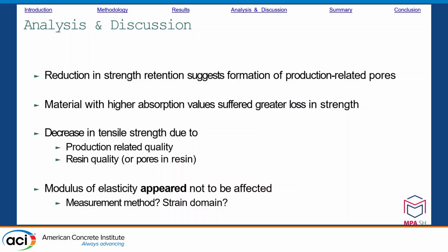In contrast to the resin matrix, here the test for horizontal shear strength, which focused primarily on the resin properties, shows significant losses due to frost exposure. The decrease in tensile strength is therefore caused more by the poor resin quality than by the fibers. Furthermore, the production quality also plays a decisive role here. Better results in the properties of the fiber rods can only be achieved if the resin is evenly distributed between the fibers in the FRP rod.